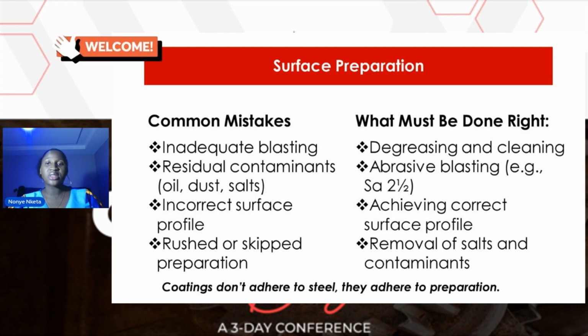So what must be done right? Degreasing and cleaning. That is very important. Abrasive blasting has been proven to be one of the most efficient ways of cleaning our substrates. So if the specification states do SA 2.5, or if it says do SA 3, you have to follow what the specification is saying and do your cleanliness to that level that the coating requires. Also, achieving correct surface profile, we've talked about that. Then removing salts and contaminants. If these things are not done properly, you're likely to have failures.